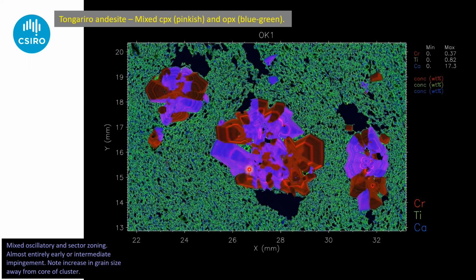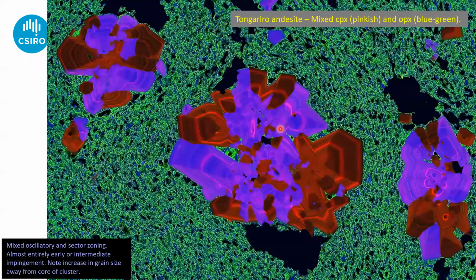And this banding here is fluctuation in the chrome content, so this is classic oscillatory zoning. But look at how the same zone seems to be traceable through the orthopyroxene and the clinopyroxene. You can also see that the grain size is really tiny in the center of this cluster and then gets bigger as we go towards the outside. So this thing starts out as a little cluster of crystals and then grows out to form these beautiful snowflake aggregates. Make of that what you will, but I think it's a really interesting phenomenon. So that's the same thing a bit bigger, in glorious Technicolor. That one's going to be on my wall fairly soon.